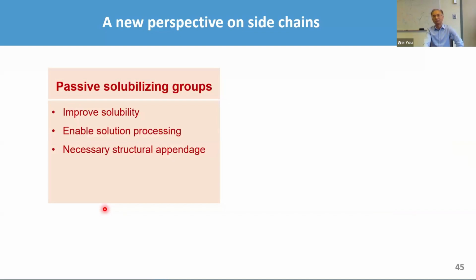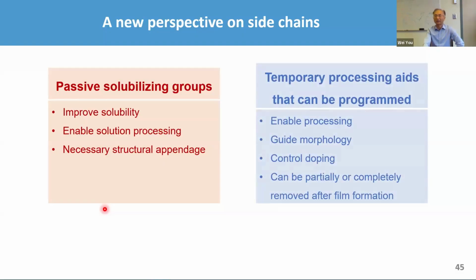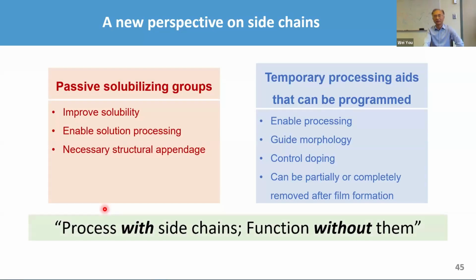So I think in the past, we talked about the side chains being passive because we treat them as the way to improve the solubility and enable solution processing. But I'm hoping that after this talk, you possibly are able to have a new perspective on the side chain, because this is essentially a temporary processing aid that can be programmed to remove. It can enable you processing, morphology, control doping, and can be partially or completely removed after film formation. So if anything can stay with you after the talk, I think this is what I created, this particular slogan, or called myself, process with the side chains, but you want to be able to function without that.